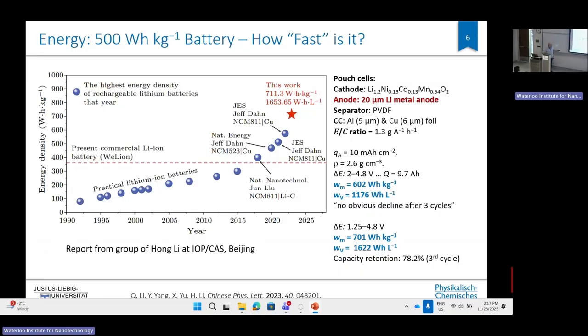So this is what has all been demonstrated, but you see beyond that red limit, there is also work by Jeff Dahn from Halifax in Canada. All these cells contain lithium metal at the negative side, which of course has a higher specific capacity, charge per mass. More lithium is stored per volume and per mass in lithium metal than in graphite, of course. So you need to employ the lithium metal electrode.